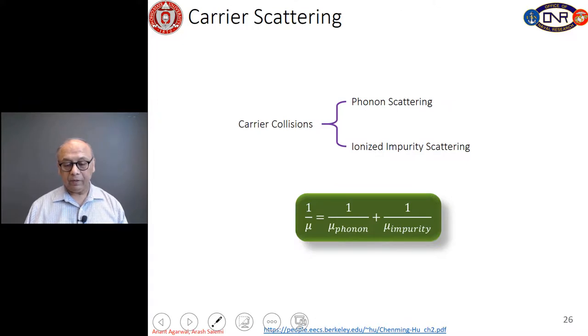So as I was saying, the two types of scattering events take place for electrons and holes. The first type is called the phonon scattering, which is the scattering by lattice atoms. The second type is the ionized impurity scattering due to the positively charged donor atoms and negatively charged acceptor atoms. Each type of scattering event describes the mobility for that particular type of scattering. And the combination rule is obviously shown here. 1 over mu is 1 over mu of phonon plus 1 over mu of impurity. And the reason for this combination rule is the lowest mobility determines the combined mobility of the semiconductor, just like two resistors in parallel.